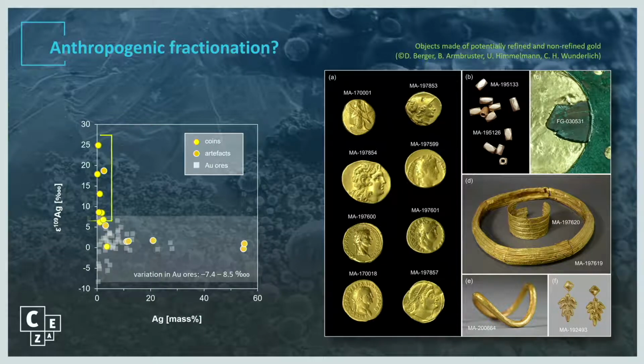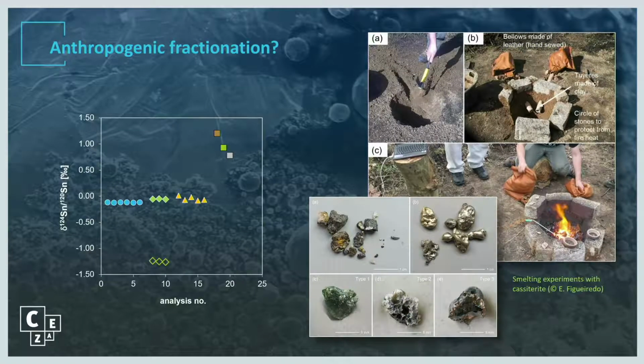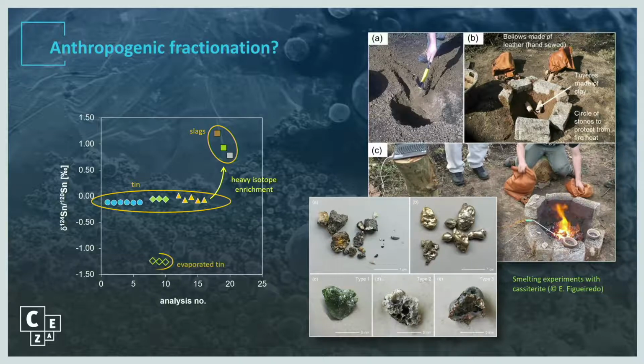So, at last, the last two slides of my presentation. This was the results of the smelting experiments that we carried out with cassiterite. What you can see here is the isotope composition of the smelted tin. When we look at the slags that we analyzed, we have heavy isotope enrichment in the slags, and at the same time we got a light isotope enrichment in the evaporated tin fraction.